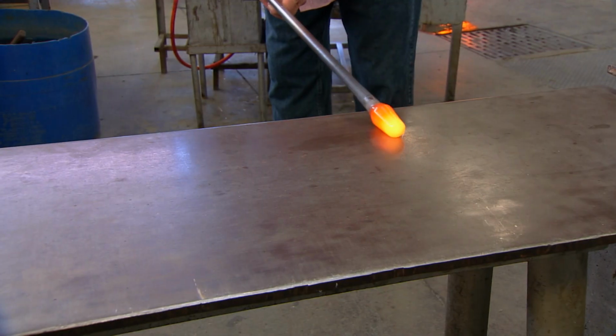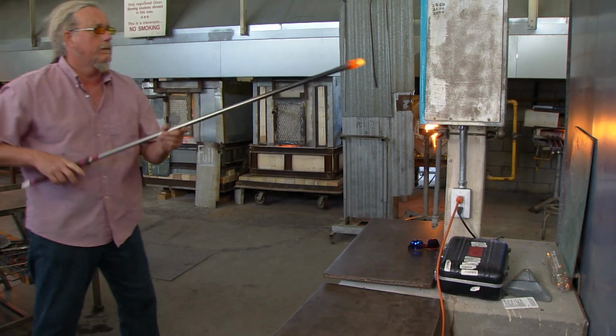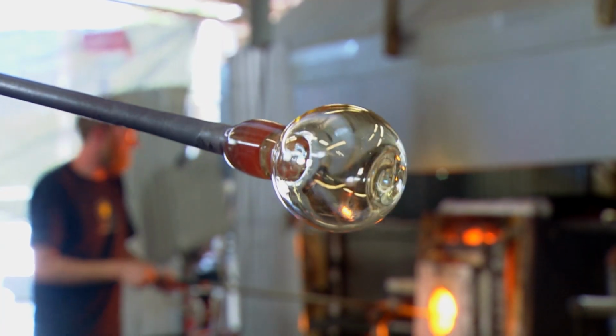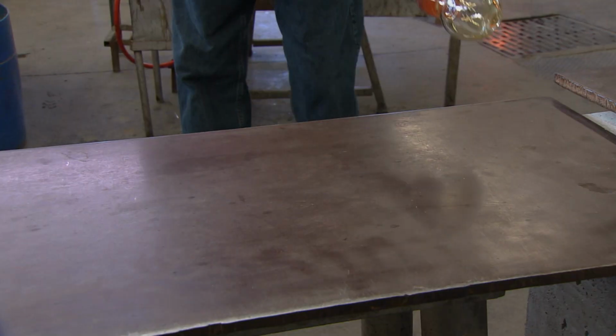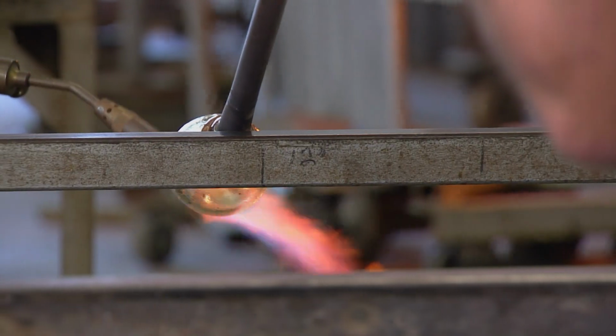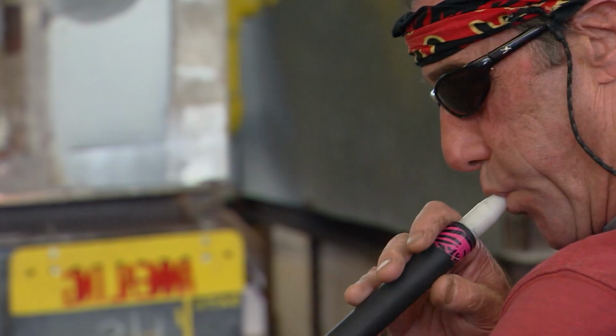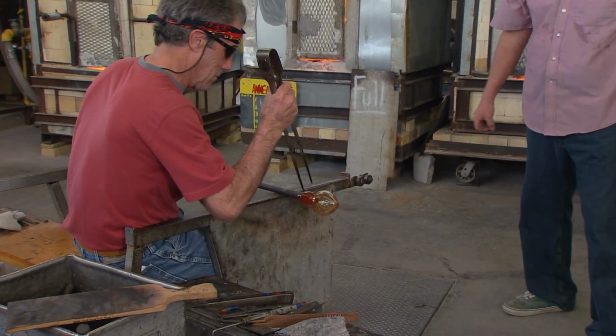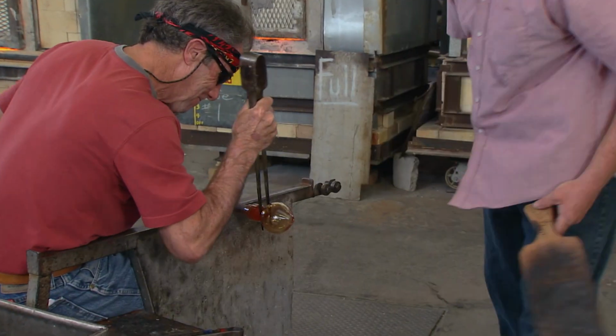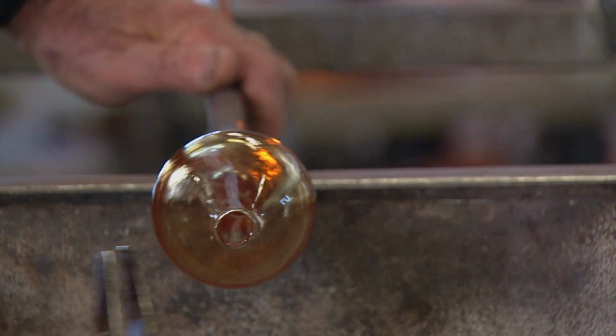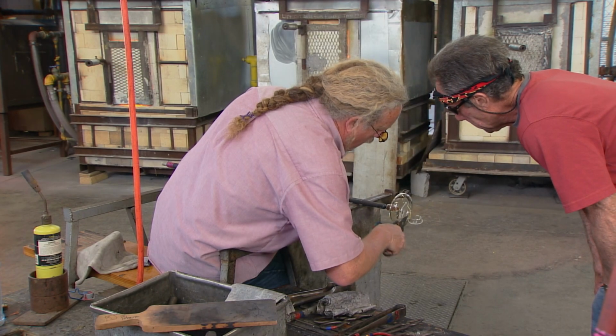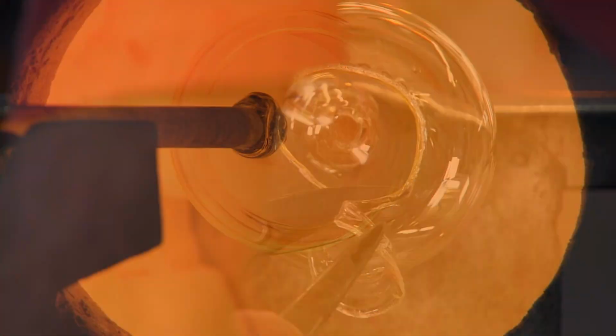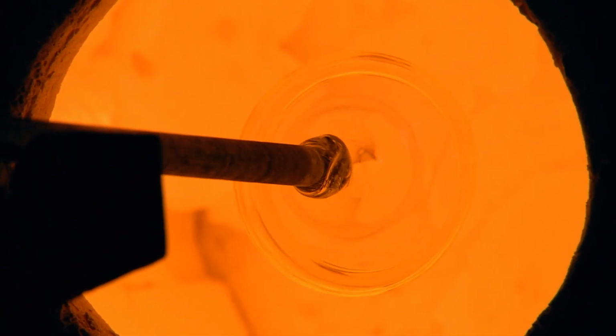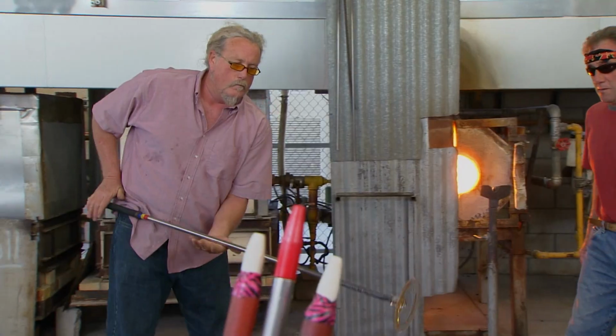We start with a little gather of glass on a hollow blowpipe. It's blown out to a certain thickness of bubble, and then we did two methods today. The first method I want to talk about is where you take a flame and heat the end of the bubble and continue to add a little pressure, and as that molten spot heats up, it pierces the bubble. Then we do a move called a necking move, whereby you squeeze the glass at the blowpipe end way down to where it just seals the bubble off. At that point, we can trim off the excess. The end is then heated to an extreme heat and spun using centrifugal force until it goes completely flat.